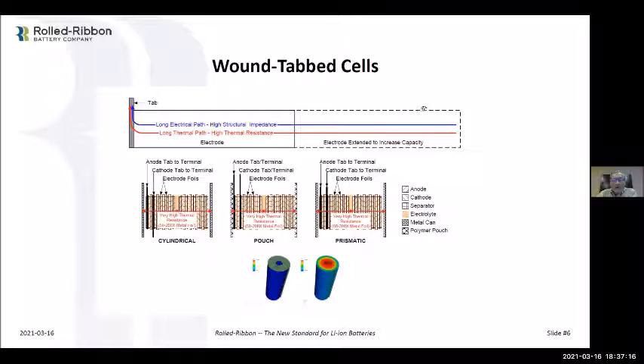And so the problem with the structure in a wound cell is you have more to wind when you want more capacity. And then when you get power delivered faster, if you want high current rates coming out of there, as we all know, that's I squared R. So you add a little resistance in the path, but as the current increases, it's the square of the current times the resistance. It's now increasing at an exponential rate. And so it becomes less and less efficient. You have higher losses. And of course, that loss translates into generation of heat. Energy's got to go somewhere. It's either delivered to the load or it generates heat.